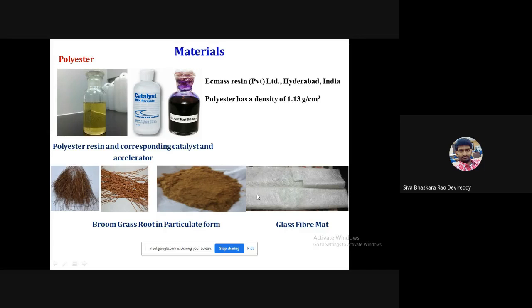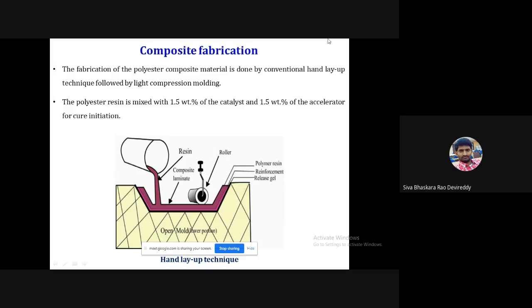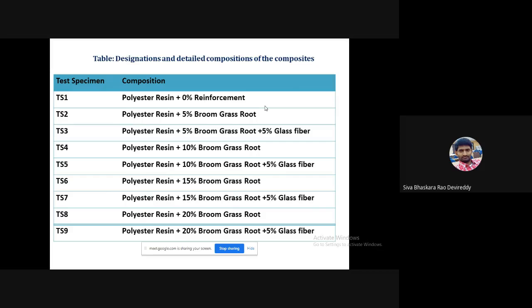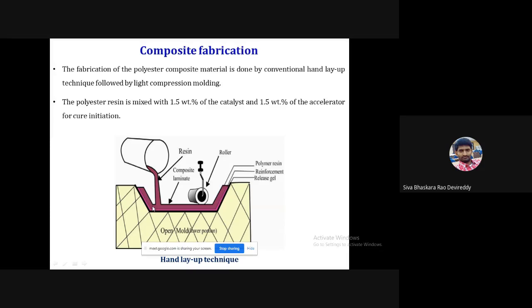Another reinforcement material selected is glass fiber mat. By using these two reinforcements and the polyester matrix, the composite is fabricated by the hand lay-up technique followed by light compression molding. For curing this polyester, catalyst and accelerator were mixed at 1.5 weight percentage each. After mixing the polyester with the catalyst and accelerator, the broom grass root particulate is added into the polyester resin, and the glass fiber is placed layer by layer.